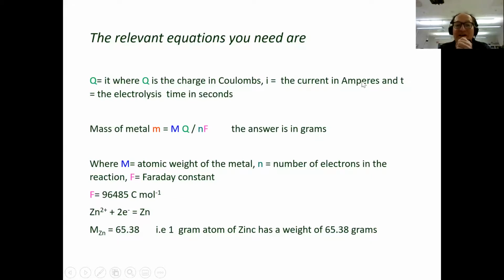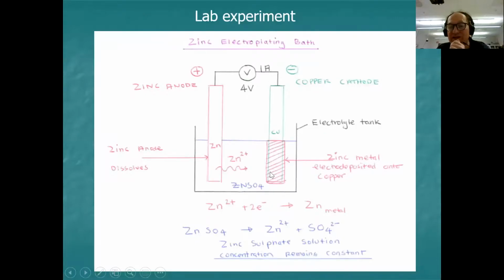So I hope you get the idea that when we determine how much metal is being put down on here, we're actually going to use Faraday's laws. And Faraday's law tells us how much metal is deposited for every single coulomb of charge we pass from the power supply. So in other words, in order to calculate how much material you're putting down, you need to know 2 things. 1 is the current in amperes, and 2 is the time. And rather surprisingly, you don't need to know the voltage for this calculation. Although this represents the amount of energy, in Faraday's calculation, in order to work out how much we deposited, we only need to know how many coulombs of charge we've actually passed. And we also need to know how many electrons there are per ion or per atom of metal. So in this case, the number of electrons is 2.